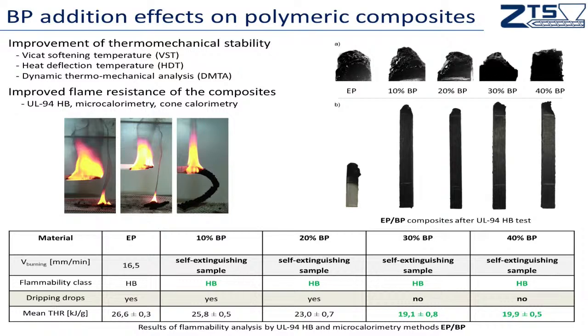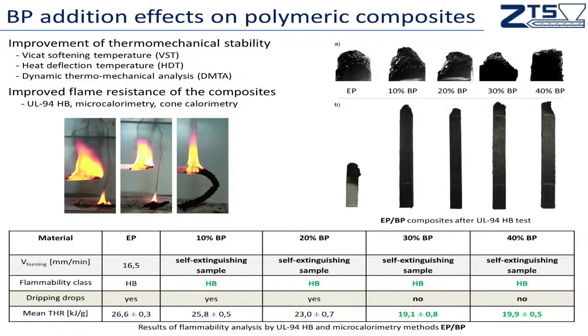promising. Epoxy composites are those which are mostly used in the automotive industry and in airplanes, so in places where flammability is essential from the safety point of view. And here we can see that addition of even 10% of the basalt powder significantly reduced the flammability. The samples were self-extinguishing during the exposure to the fire.